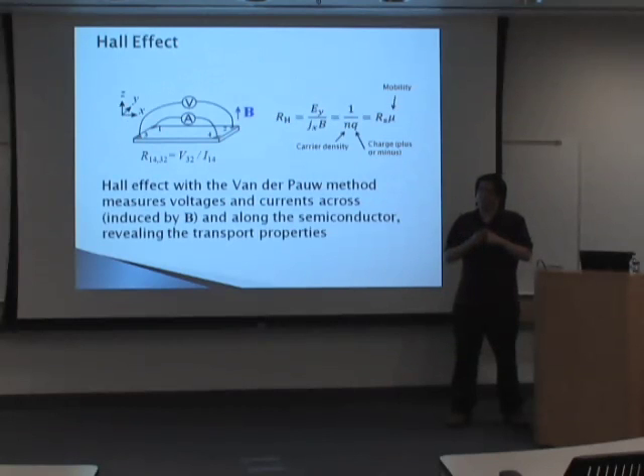And to measure the performance of your semiconductor, we use the Hall effect with the setup called the Van der Pauw setup. Now the Hall effect is the creation of voltage across your semiconductor under an external magnetic field. Typically the current flows only along your semiconductor, but the Hall effect introduces voltage across it. And when you have it arranged with the Van der Pauw setup, you can calculate the sheet resistance, and in conjunction with the Hall coefficient from the typical Hall effect experiment, you can reveal a lot about your semiconductor.